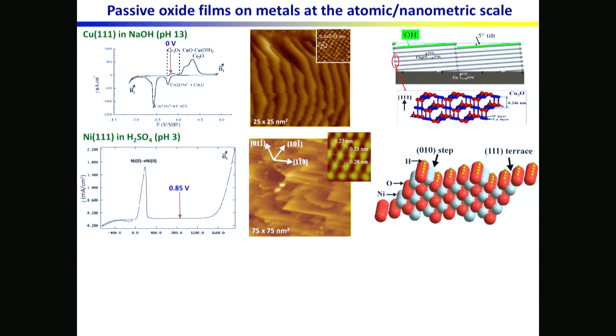And what I'm showing here is one of many images that we recorded, and this was recorded at potential, which is indicated here, 0.85 volts. And again, there are two images here. One is on a fairly large scale, I mean, on the scale of a scanning tunneling microscope, 75 by 75 nanometer square. And this is the high resolution image, again, obtained in situ while we were polarizing the sample and measuring the Faraday current. We also recorded these images, and this is again a non-filtered image in the direct space from which we can deduce directly the structure of the oxide.